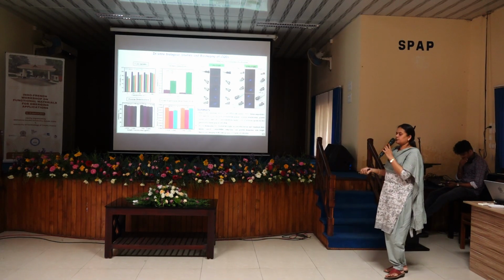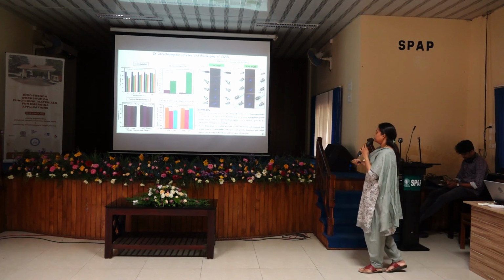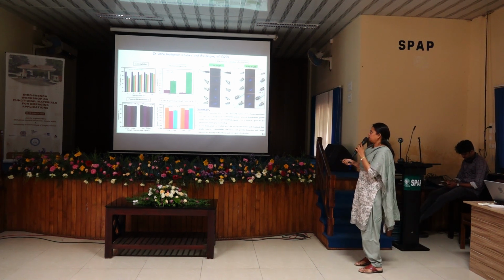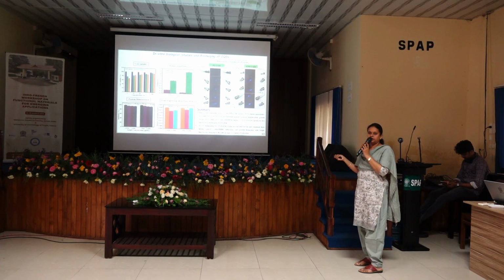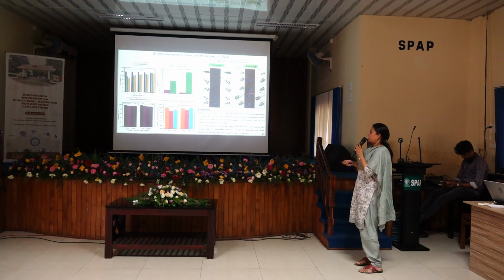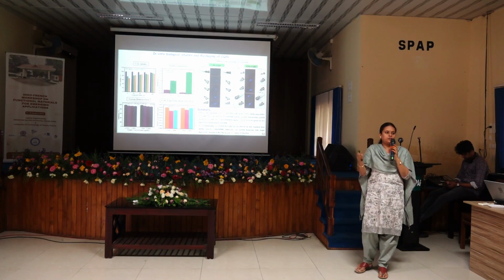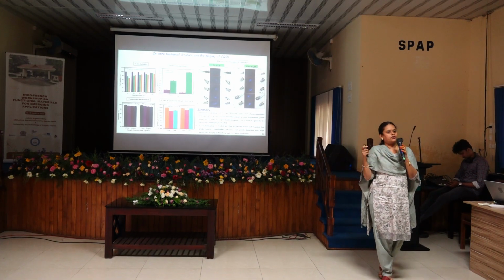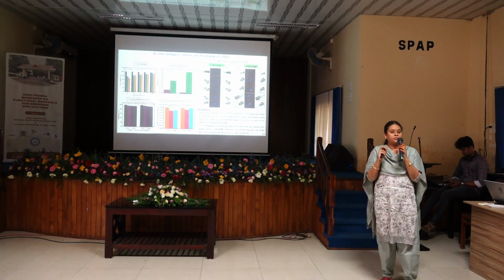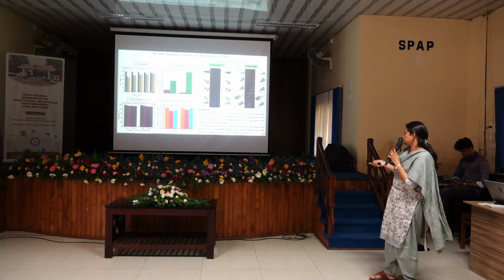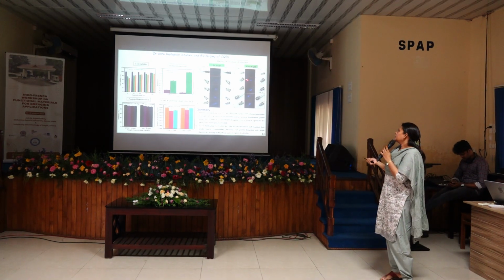Further, the in vitro studies have been carried out for the CQDs. The cell viability is around 98%, hemolysis is only 3% and 5%, and protein denaturation was also assessed, along with the gene expressions for IGF and collagen. Insulin-like growth factor and collagen genes have shown a stimulatory effect for the CQDs.